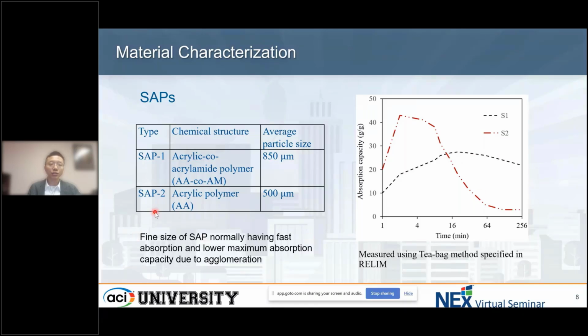And for the SAP2, it is an acrylic polymer with an average particle size of 500 micrometer. It represents the red one. So it absorbs water very quickly in the first 3 minutes. But after that, it desorbs water also very rapidly, and in around 1 hour, 90% of the water has gone. So these two different types of SAP have different absorption and desorption capacities.